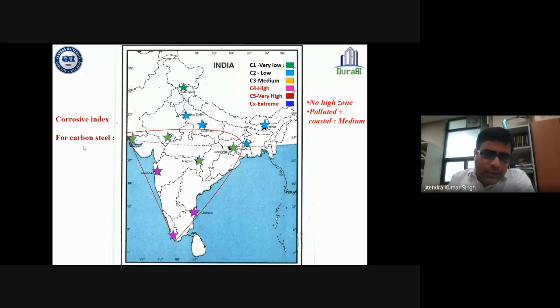It is for Mumbai, Chennai, Trivandrum, Kolkata. This portion is polluted as well as coastal area. In this area, it is a medium coastal area. You can see there are different corrosivity indices: C1, C2, C3, C4, C5, and the extreme condition. Mumbai is C4. It's a high corrosion rate, not very high, not extreme. Chennai also has a high corrosion rate, and Kerala, I mean Trivandrum, also has a high corrosion rate. But as you move to Jorhat, Lucknow and New Delhi, the corrosion rate is low.